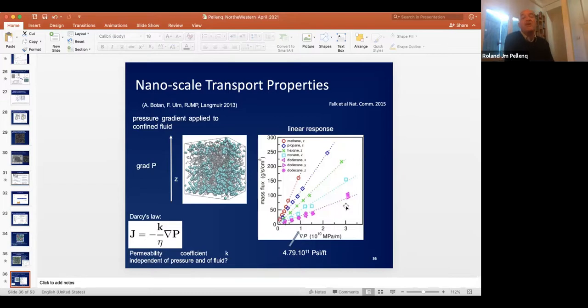So we are applying a pressure gradient to the simulation. And we can calculate how many molecules go through a surface area, that's the size of the box, per unit of time, okay? That would be a flux. So if we study the flux as a function of the pressure gradient, then we are studying Darcy's equation. All right, Darcy's is this linear response theory where the flux is actually proportional to the pressure gradient. Fine. And there's a constant in between. In Darcy's formulation of the flux, this constant is actually the ratio of two quantities.